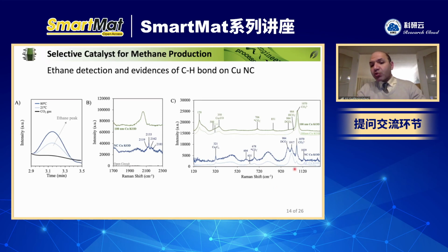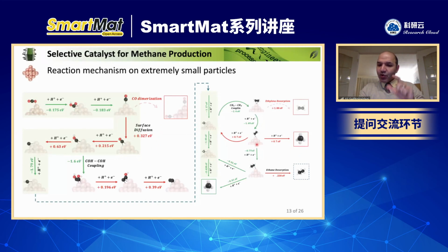So we were able to observe the CH bonding, the CH vibration, and also we observed the CC adsorbed on the surface. So on very small nanoparticles, we observed a higher population of the CH bond, as you see here, and CC bond. But on large particles, we didn't observe those features, which was kind of supporting the idea that if you have a small particle, these species should remain on the surface. But again, to answer the time resolved question, no, we didn't have the facility to run it, but that's also an interesting question.